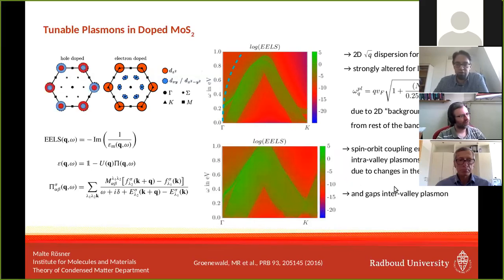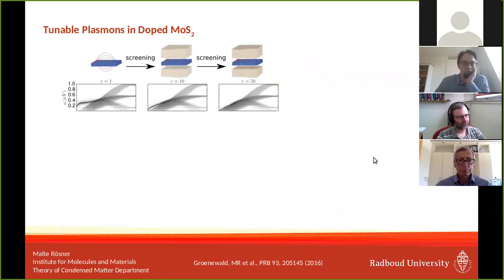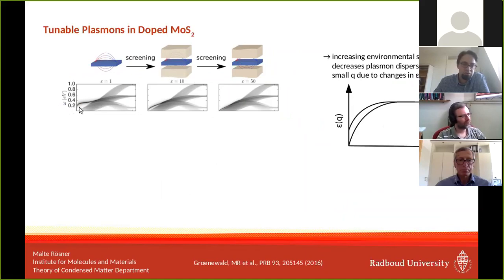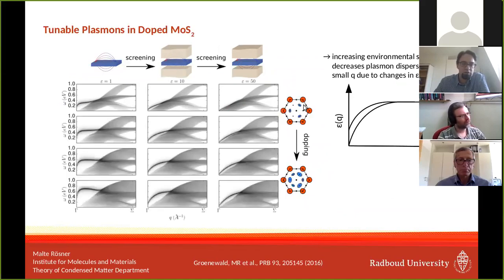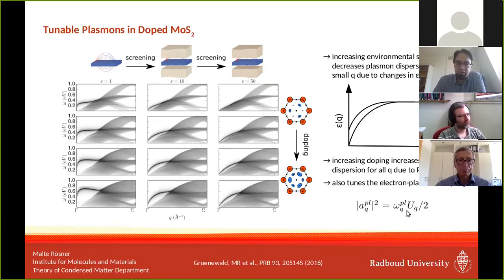We can also show how plasmons can be tuned by the substrate. When we change the environment, we change the screening, which changes the epsilon function and thereby pushes down the plasmon dispersion for small momentum. At the same time, by increasing the doping, we increase the dispersion everywhere, gaining quite some control on the plasmon dispersion depending on screening and doping. This is something we are investigating in detail and might be extremely important for the electron-plasmon coupling in the context of plasmonic superconductivity.